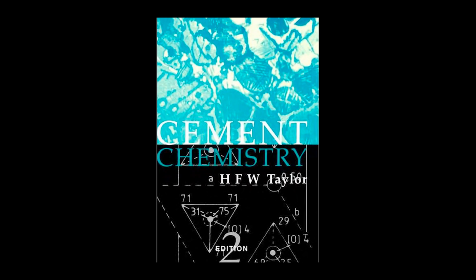That's a key microstructural insight, and the CSH gel itself is fascinating. It's poorly crystalline, sometimes described as quasi-amorphous, but it derives its structure from a natural mineral called tobermorite. However, cement CSH has structural defects, missing silicate tetrahedra, and a much higher Ca-Si ratio, typically 1.5 to 2.0 in C3S pastes, compared to tobermorite's lower ratio.